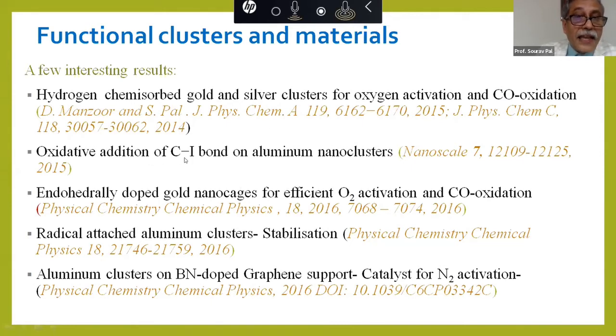Oxidative addition of the C–I bond on aluminum nanoclusters. Aluminum nanoclusters are used for oxidative addition of the C–I bond. One of the interesting clusters, again, is the endohedrally doped gold nanocages. I will show some of this result again. Radical attached aluminum cluster. And a very interesting catalysis that we have found is an aluminum cluster on boron nitride doped graphene. This has a very promising result for dinitrogen activation. And I must say, again, I am not very sure if such a catalyst can be synthesized.